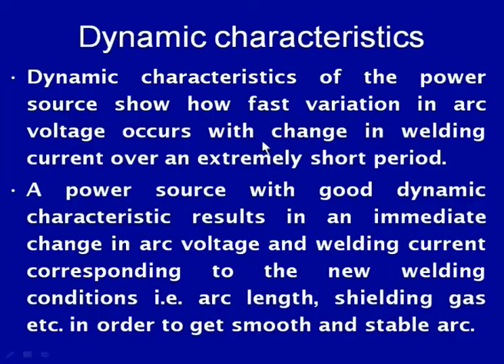The dynamic characteristic of the power source shows how fast variation in arc voltage occurs with the change in welding current over an extremely short period of time. A power source with a good dynamic characteristic results in immediate change in the arc voltage and welding current corresponding to new welding conditions, that is, the arc length or the shielding gas, in order to get a smooth and stable arc, so that the heat can be generated uniformly and the melting can be obtained as desired.